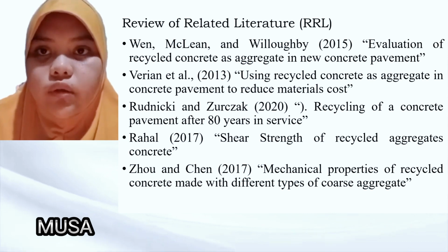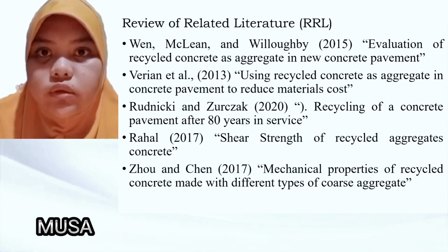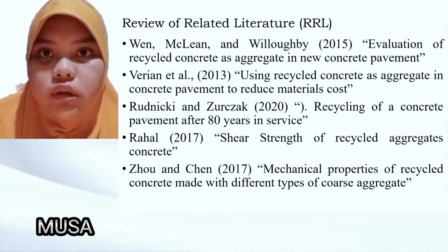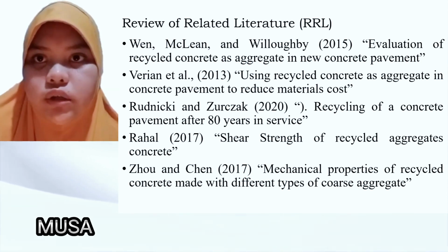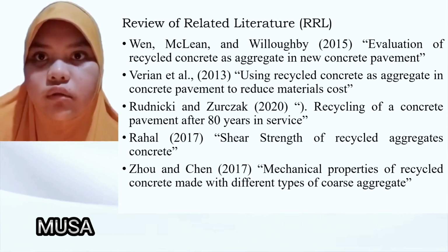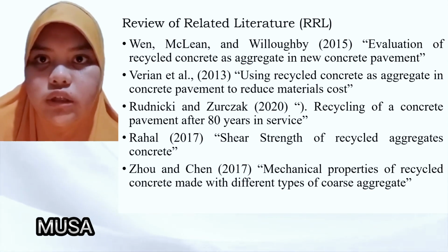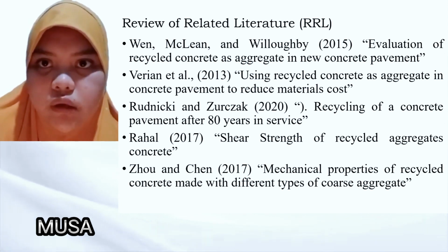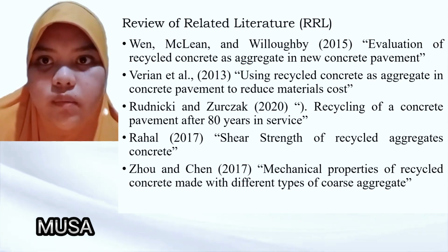Review of related literature. Studies by Wen, McLean, and Willoughby in 2015 have shown that using recycled concrete aggregates, or RCA, in concrete pavements can lead to reduced cost, decreased environmental impacts, and faster project delivery times. Rudnicki and Zurczak evaluated the compressive strength of recycled concrete from the A6 motorway pavement using an EN 12390-3:2019 test process, finding values of 65.8 megapascal for the upper layer and 51.2 megapascal for the lower layer. This meets specification for various types of road construction.